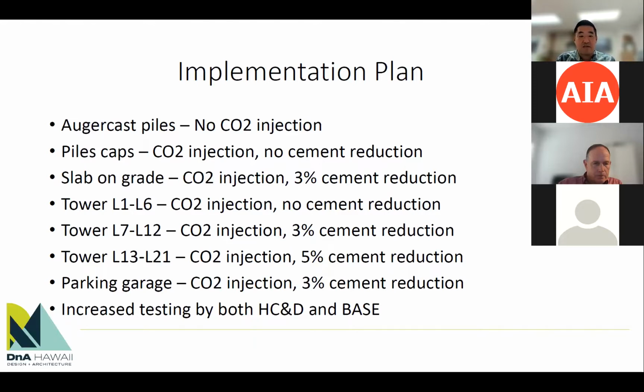So the auger cast piles, the foundation of the building, we didn't touch the specialized mix design. We just left them as they normally are installed in Hawaii. On the pile caps, we injected the Carboncure, but we didn't reduce any cement. At the slab on grade, we did a 3% reduction instead of the desired. The desired reduction, optimal reduction, is 5%. So at the pile caps, and then the slab on grade, we did 3%.